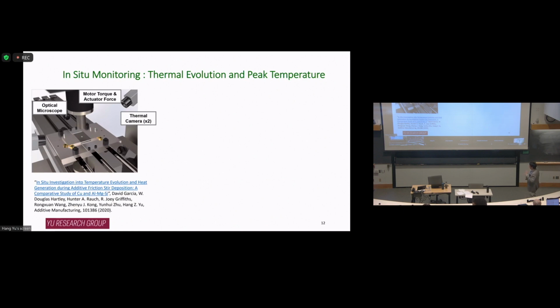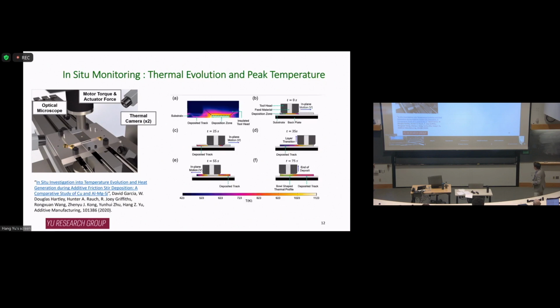So from that, we can try to understand how the processing parameters affect the thermal characteristics. Right? One example is here, just from a thermal camera. This is the material deposition zone. This black thing is essentially my tool. I cover my tool to make sure there's no interference from the tool signal. So I just focus on the deposit material, and of course, we can measure the entire thermal field as a function of time. And this is an example of copper deposition.